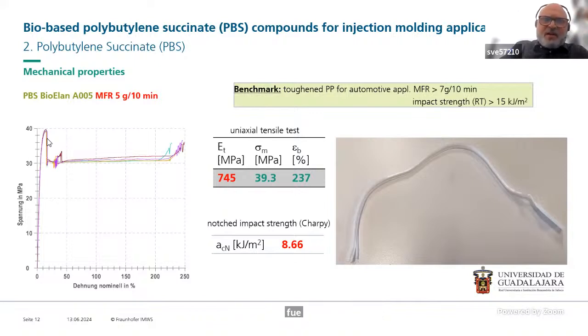And you can see immediately that we have a beautiful polymer. It's very similar to polypropylene, actually. You can see that the maximum stress here is approximately 40 megapascals. We have an elongation at break that is going up to 250%, which is really good, in the range of polypropylene. But if we want to go to automotive applications, we have to improve the stiffness. Here, the modulus measured in the tensile experiment is quite low, lower than we would need. And we still have a problem with the impact strengths, especially the notched impact strengths according to Charpy.